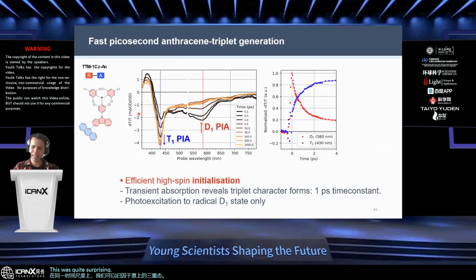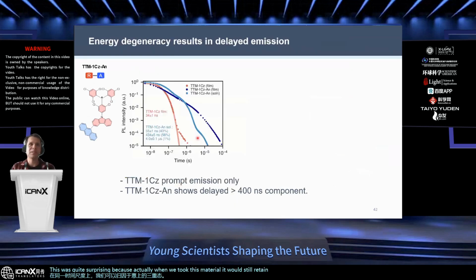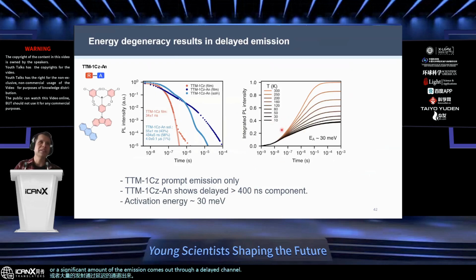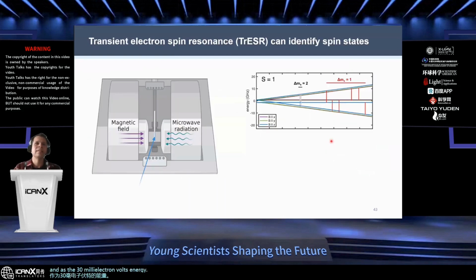This was quite surprising because actually, when we took this material, it still retained a high photoluminescence quantum yield. And that's because a significant amount of the emission comes out through a delayed channel. In fact, you can think of these materials as sort of radical thermally activated delayed fluorescence materials in which you can activate this delayed fluorescence. It has a 30 milli-electron volts energy.